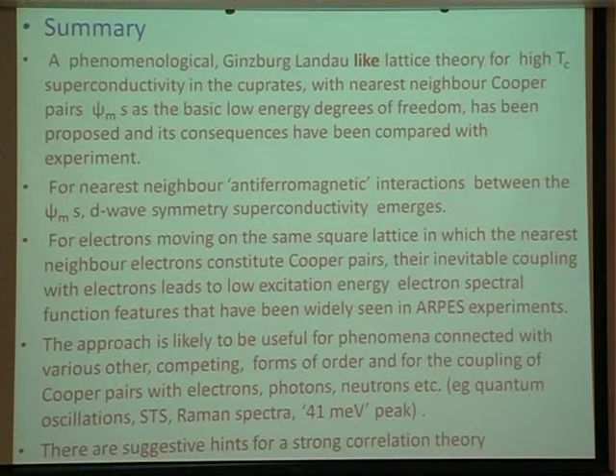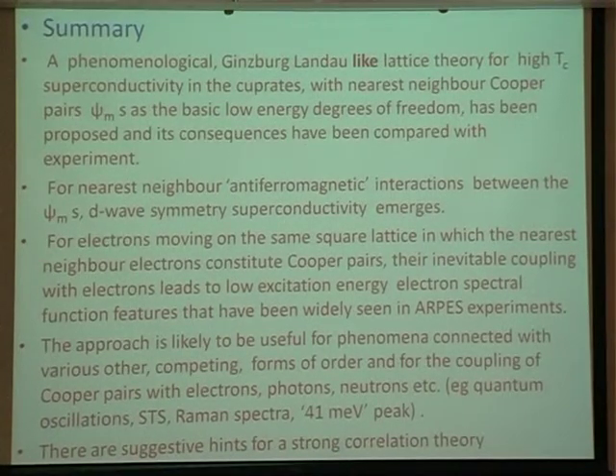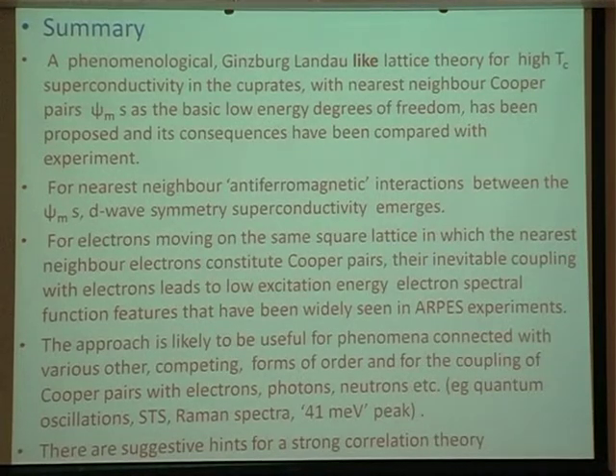So, all right, let me summarize. We have developed and looked at the consequences of a phenomenological Ginzburg Landau-like lattice theory for high temperature superconductivity in the cuprates with nearest neighbor Cooper pairs as the basic low energy degrees of freedom. Then we find that if the interaction between these degrees of freedom is antiferromagnetic, then D-wave symmetry superconductivity emerges. For electrons moving on the same square lattice in which the nearest neighbor Cooper pairs live, they have to couple to each other, and this coupling leads to low excitation energy electron spectral features which are seen in ARPES. I think there are some suggestions that a strong correlation theory would be natural for that. Thank you.